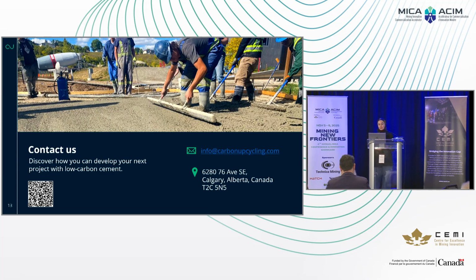Okay, so in this case, we are using different feedstock, which is mainly different waste materials. We want to selectively extract some critical minerals while keeping the matrix as it is. That's why we're applying different steps in order to extract the target metals without dissolving the matrix. So we have more than one step: a thermal step, filtration, and also some washing steps. In terms of energy, we are now trying to scale up and to work out the capex for this process, and to see how much energy we need to achieve this goal.